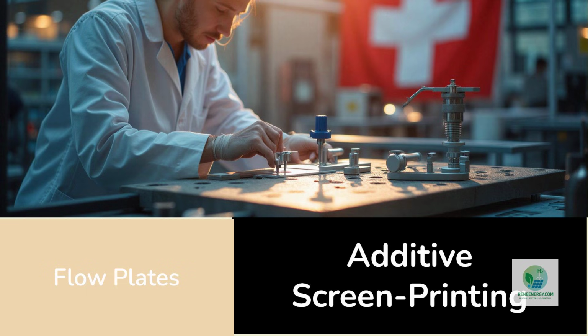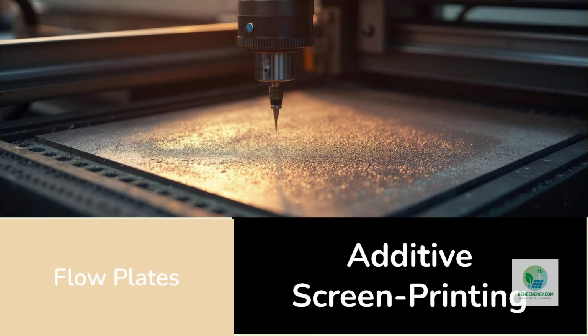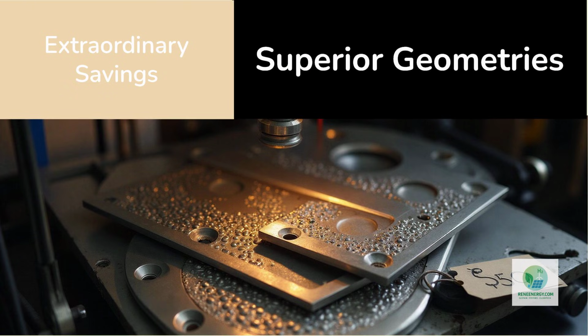But in Switzerland, a quiet revolution is underway. Exentis Group, a pioneer in high-precision additive screen printing of metals, developed a platform that prints fully formed stainless steel plates with microchannels as thin as 125 micrometers. Instead of machining away 90% of the metal, Exentis prints only what is needed. Their machines can produce more than 1,000 plates per day, not by stamping, but by digitally depositing the metal in exact shapes.